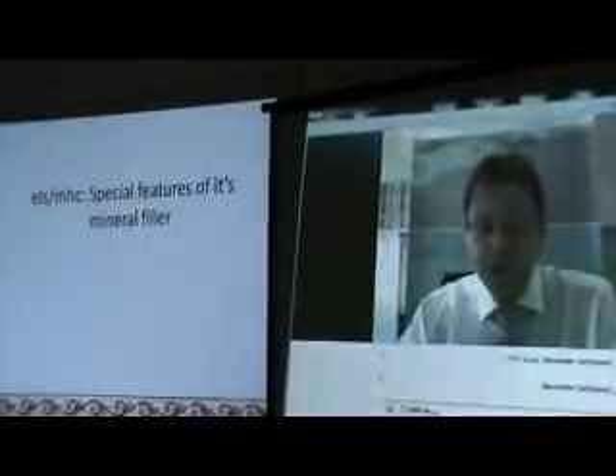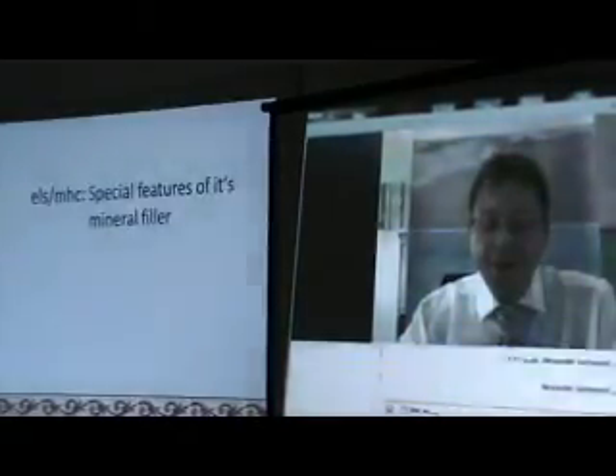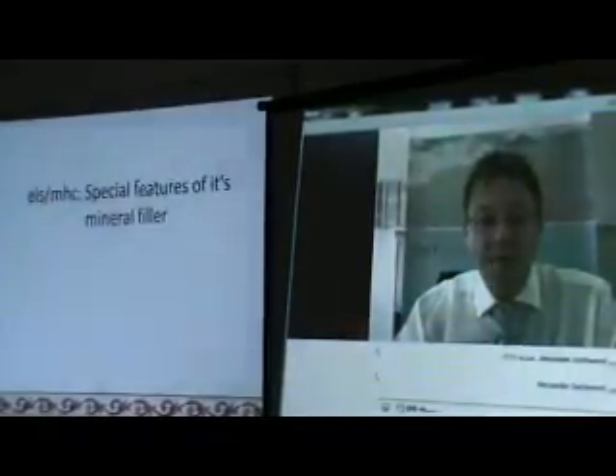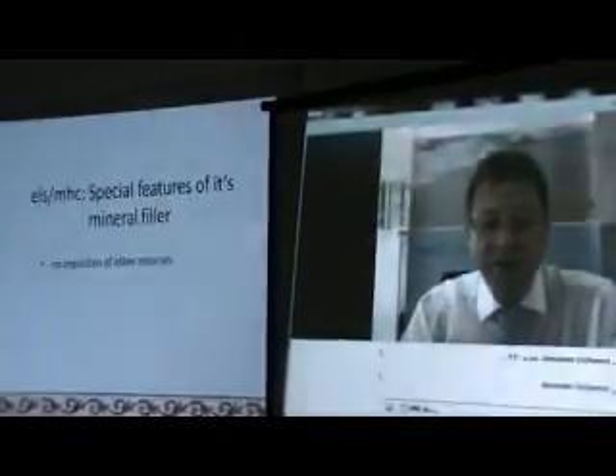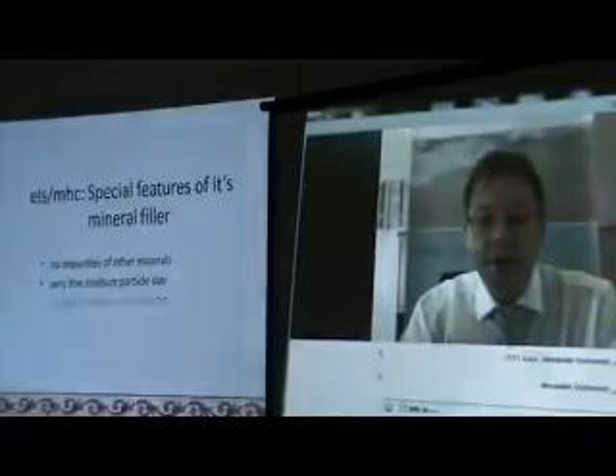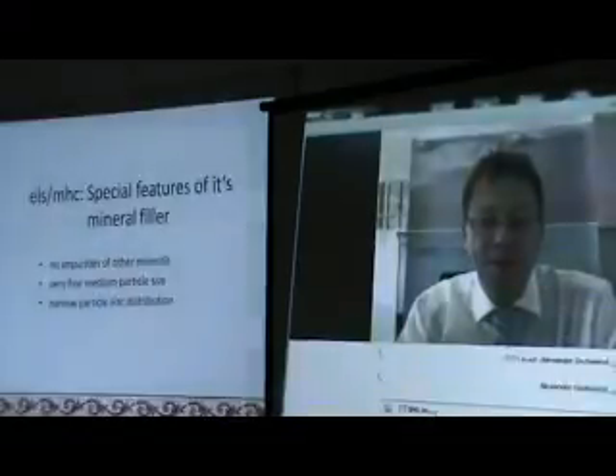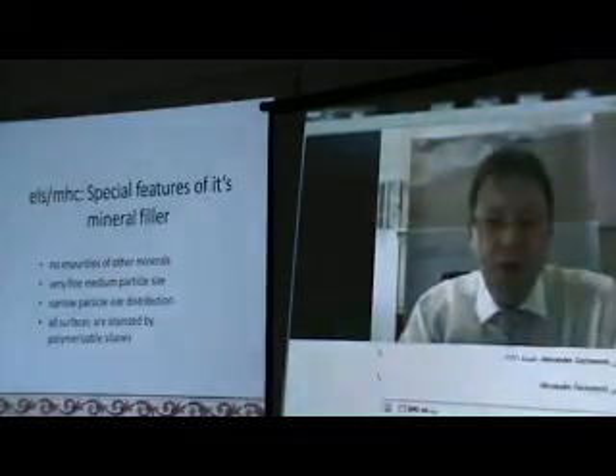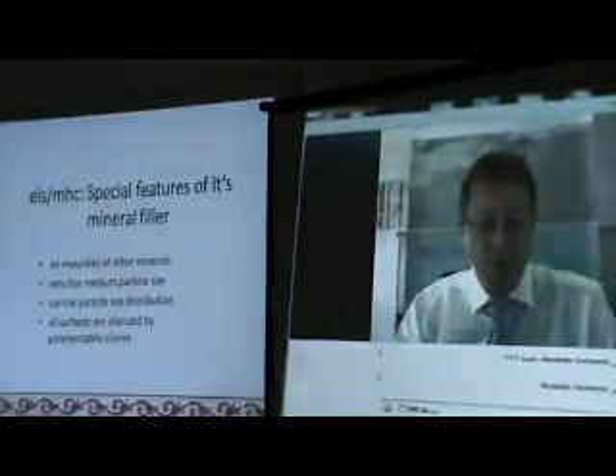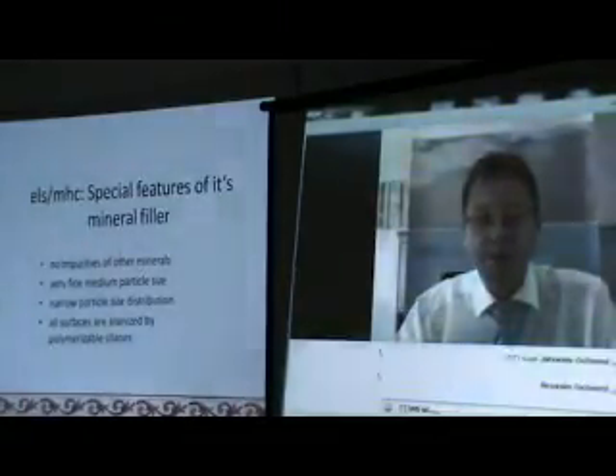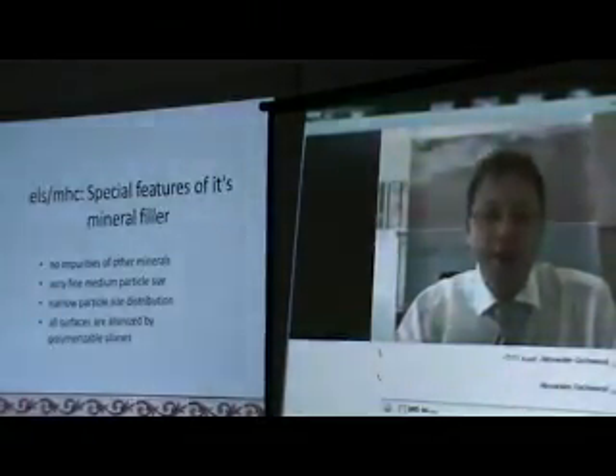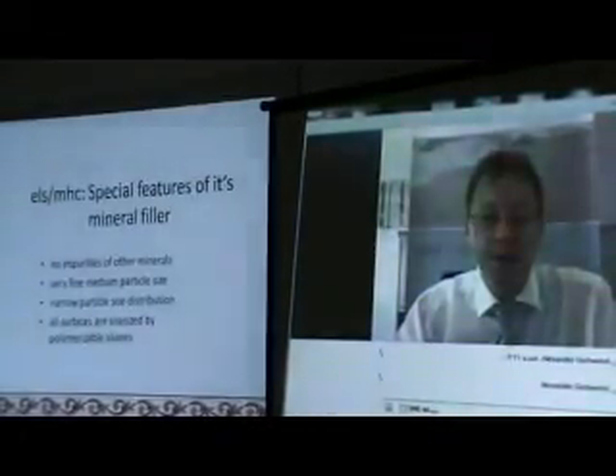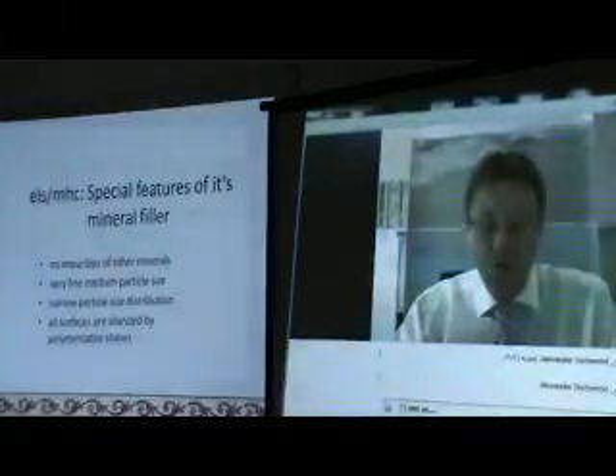Saremco products use very pure and very homogeneous bioglass fillers. Saremco composites are made of very pure glass fillers. There are no impurities at all. We have a very fine medium particle size. The particle size distribution is very narrow. That means we have small particles, but there are not much smaller and much bigger ones. So the size of these particles is extremely homogeneous. This is a sign of good quality of a composite, because it will help you to make an extremely easy polishing, and also to have a surface where no bacteria can attach, and therefore where you can have a very long-lasting restoration without discoloration of the restoration itself.